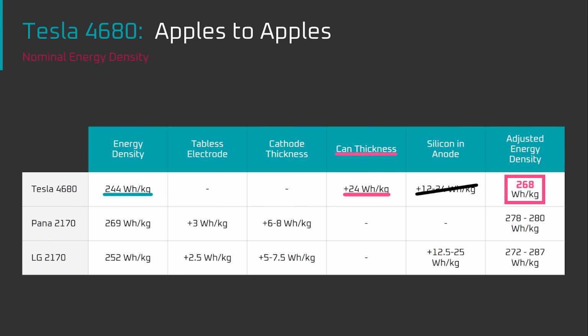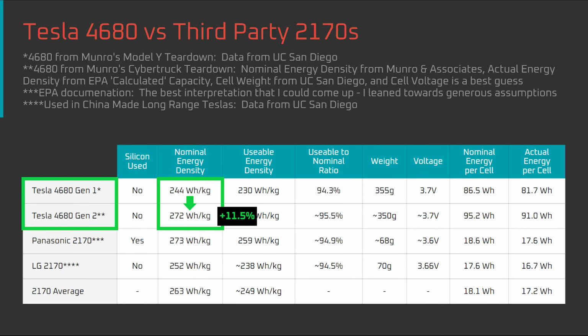83% of 24 watt-hours per kilogram would mean a 20 watt-hour per kilogram increase in energy density. If the Generation 1 4680 was 244 watt-hours per kilogram, that would mean a hypothetical energy density increase to 264 watt-hours per kilogram simply by making the cell can thinner. However, as we saw in the previous video, the measured energy density of the Generation 2 4680 is 272 watt-hours per kilogram, which means there's clearly also an improvement to the chemistry of the battery cell.